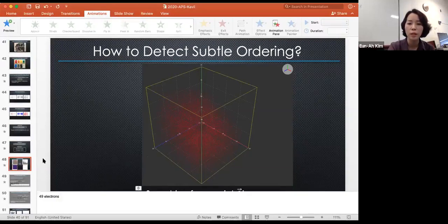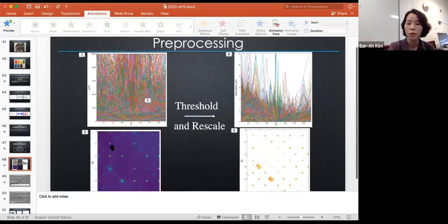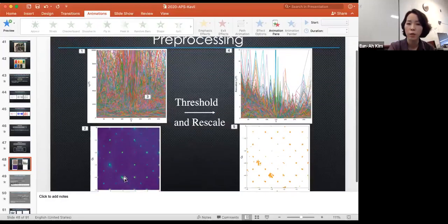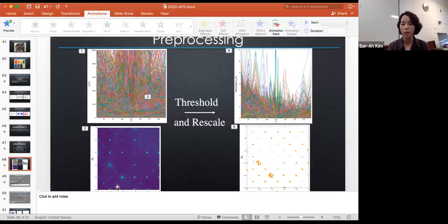What you're going to get is something like, at the lower left corner here, this kind of distribution. And if you were lucky, the plane you have chosen would have cut the plane where the charge density wave peak is located. Then you will see that show up as you lower the temperature. So you make these various cuts and you observe by human eye inspection. That's literally how it's done, human eye inspection.